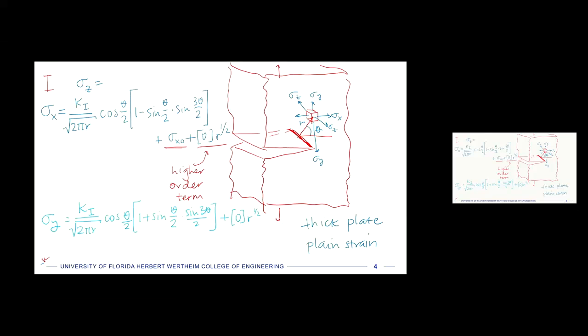In this case, we have this stress field, and I'm trying to reconcile that addition that we had of sigma x naught here in the first one as a far field term, but that's not included in the second term, even though sigma y, the normal stress in the y direction, is what we have in this coordinate system for mode 1 opening. So I'm wondering if that's an error in the book where it needs to go on y instead of x. I'll have to go back and look at that. Otherwise, the terms are very much the same.